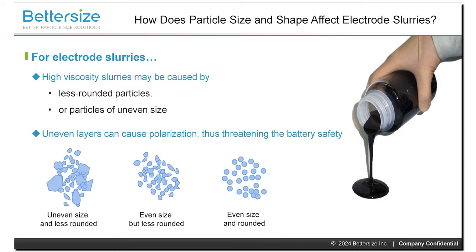For mechanical properties, particle size influences the integrity of the electrode, affecting its resistance to mechanical stresses during battery cycling. Certain shapes, like flakes and fibers, can also enhance the flexibility and mechanical stability of the electrode structure, and this reduces the risk of cracking or delamination. So, optimizing particle size and shape allows for the development of electrodes with improved energy density, power output, cycling stability, and overall performance.